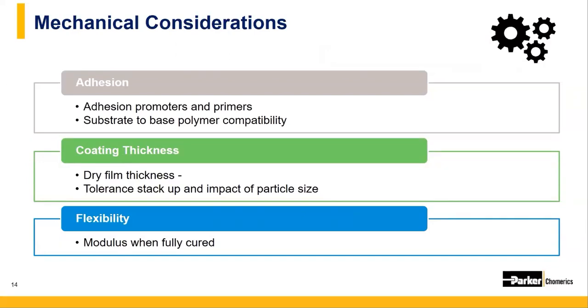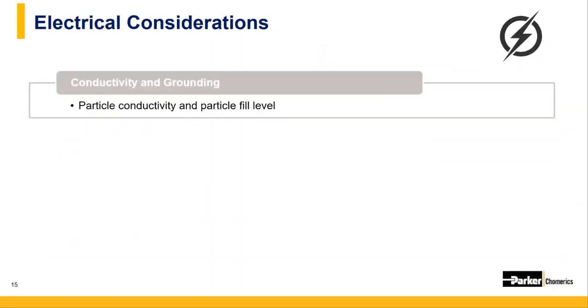Greater coating flexibility is a benefit on substrates that are subject to thermal expansion and contraction, as well as intended or unintended flexing or bending. Because we're talking about conductive paints, we need to know about the electrical properties. Lower conductivity filler systems are often associated with lower levels of shielding and more cost-effective solutions if the shielding requirements are moderate. But as with other solutions, the overall conductivity is driven by the individual particle conductivity as well as the level of fill in the paint.